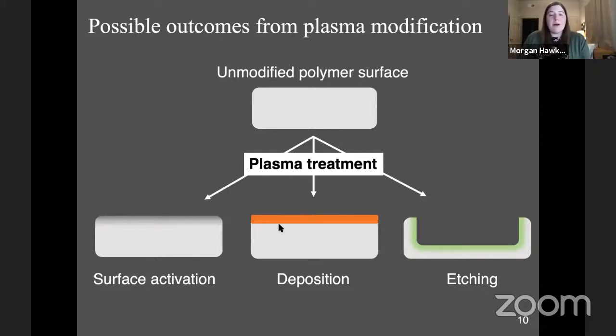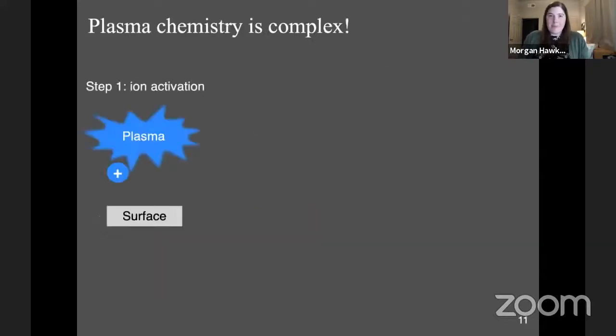So for example, a particular set of plasma conditions could result in deposition and then etching of that deposited film, depending on the relative concentration of different species in the gas phase and their energies. So as an example, I'll show you a process that's heavily simplified to illustrate how the deposition of a film can occur in the plasma.